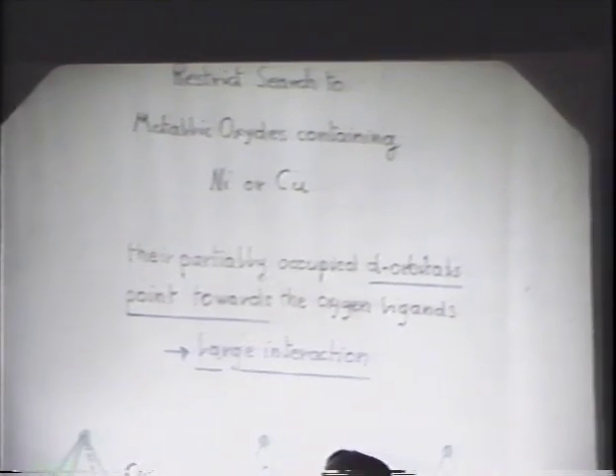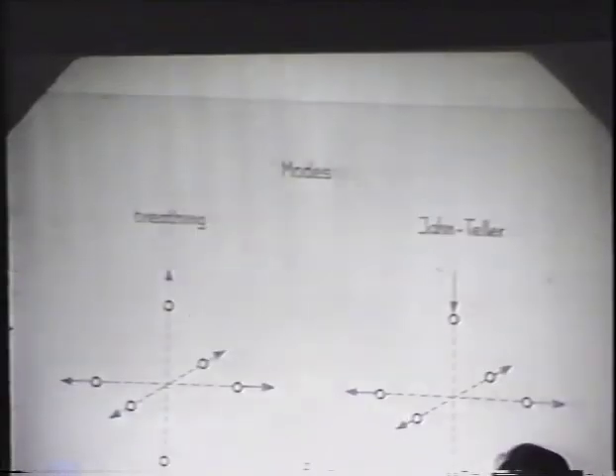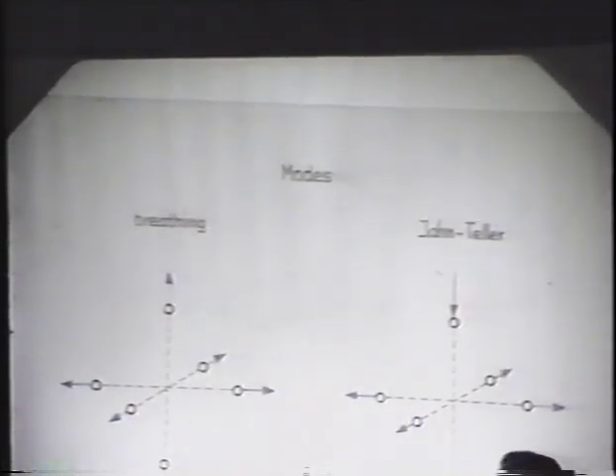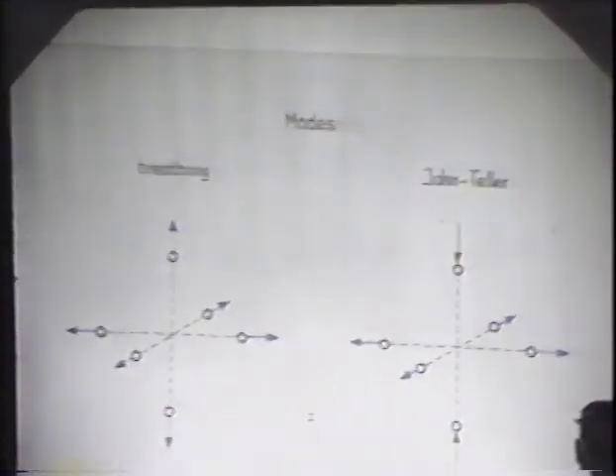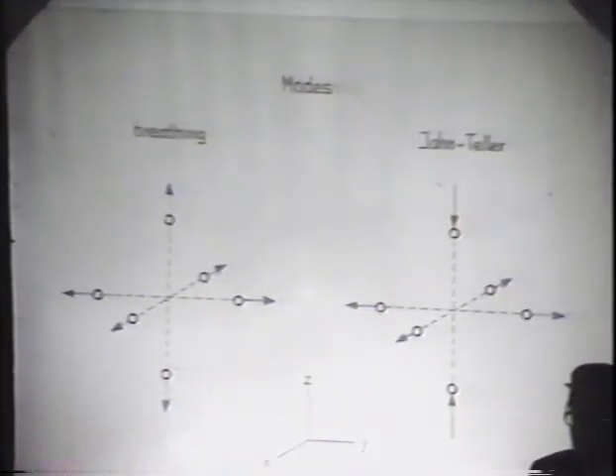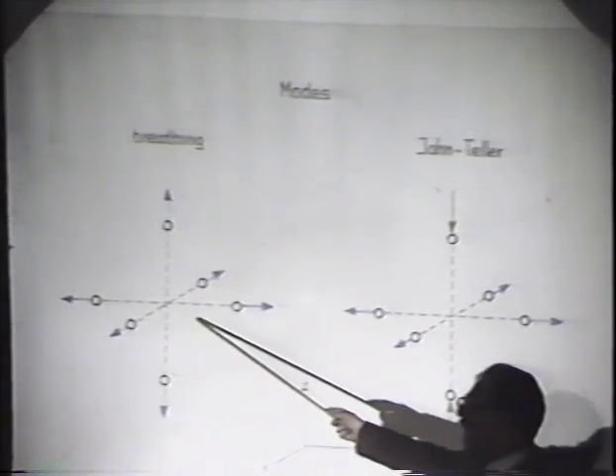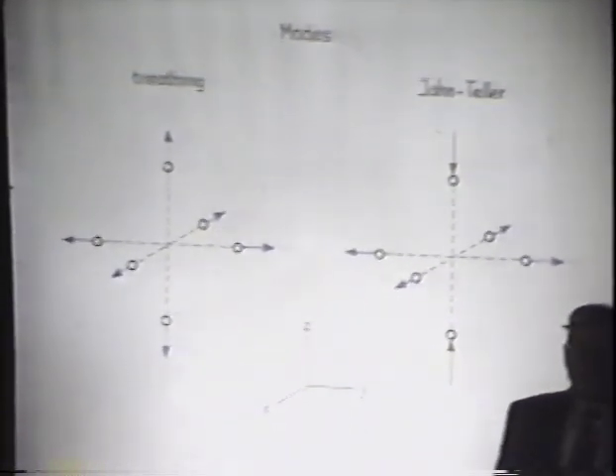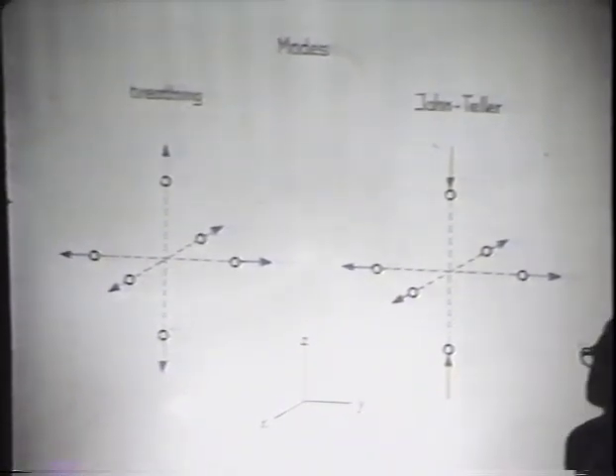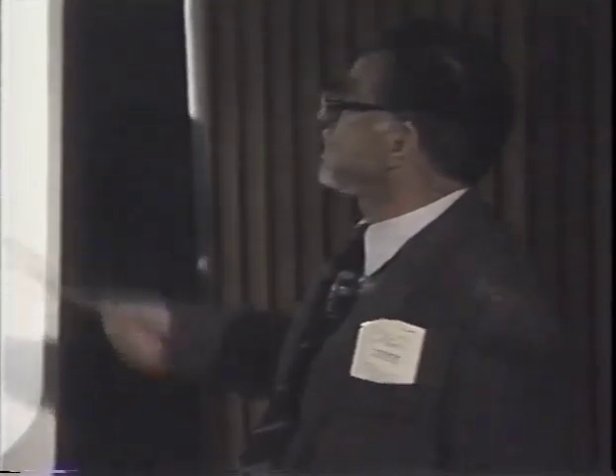Now, another thing is: what is the interaction? How does the oxygen move? Well, you have basically two modes, a breathing mode and a Jahn-Teller mode. The breathing mode is shown here. It changes the volume, and the breathing mode is very attractive if you have, say, bismuth or lead, like in the bismuth-lead perovskite, because the bismuth and the lead tend to disproportionate. So this is a disproportionating mode in a way. On the other hand, here is the Jahn-Teller mode.